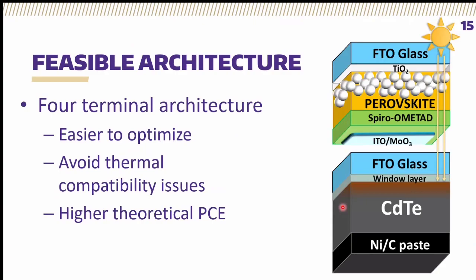The only feasible architecture really is this suboptimal 4-terminal tandem. To sum up all the reasons why I say suboptimal, the CdTe is the narrow band gap material in this tandem, which it should be the wider band gap material, but perovskites don't go low enough. And the 4 terminals are commercially less viable because of the increased balance of system costs, meaning that it is unfortunately probably not going to be very attractive for PV developers in the field.